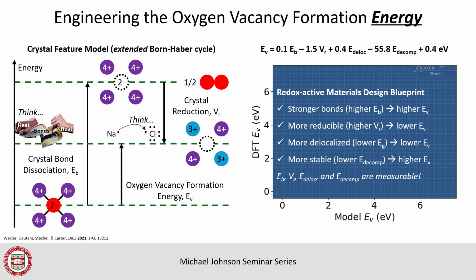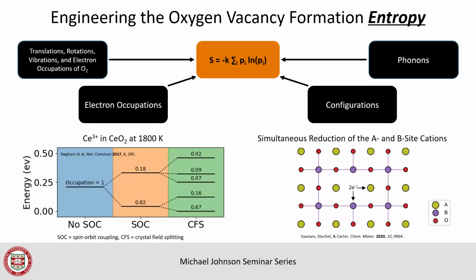We also need some other features. The last feature there is related to stability. It actually turns out if you are less stable, you're more predisposed to form missing atom defects in your crystal, because that's one mechanism by which a material decomposes. So all of these things tell us something. We can compute these all. In fact, all of these different features, bond strength, reducibility, stability, I can look that up in a thermochemistry data reference. So I don't have to do a calculation. I can just go to the library or search the web and find the particular values I need, make a prediction, and it's always going to be pretty close.